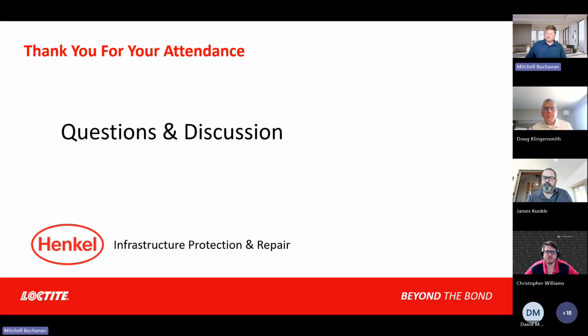Yep. So for most, we consider 827 HB a surface tolerant coating. What that means is there is acceptable, better and best type surface prep, right? Better or best being if you're doing a near white metal blast, or even white metal blast, solvent wipe, clean all your chlorides off. That's going to get you the longest term performance.